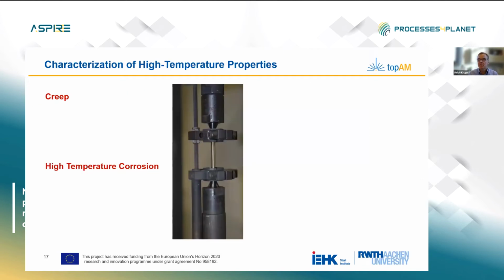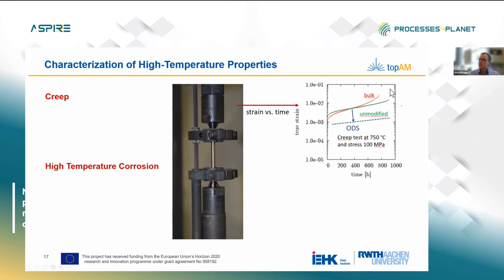And finally, what I would like to show is our characterization. We are doing creep testing and high temperature corrosion testing within the consortium. Right now we are able to show that our unmodified laser powder bed fusion alloys have rather the same properties as bulk alloys, but we also see ODS, so we are aiming at much lower creep rates.